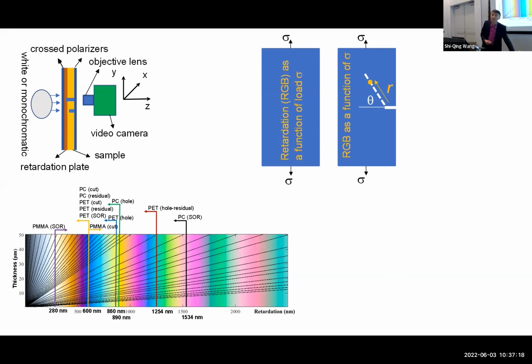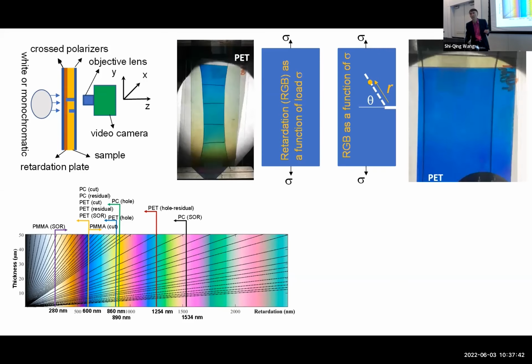We're going to try to read the stress at the tip because I'm a believer that the fracture occurred because the stress at the tip exceeded the inherent strength. In other words, it's a stress argument rather than an energy argument per se. So let's see how far it goes with this. You take one with a cut, one without a cut, and you do birefringence, which is a good way to at least have some indication